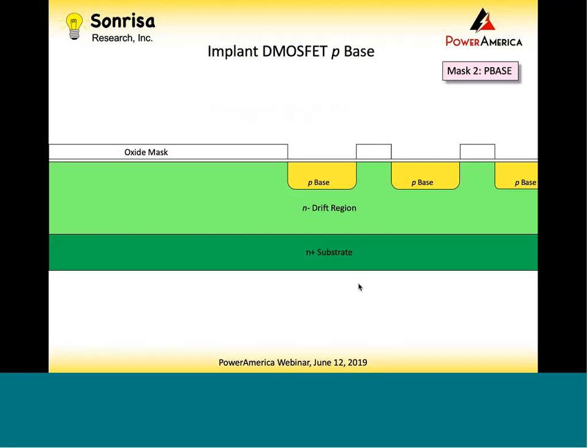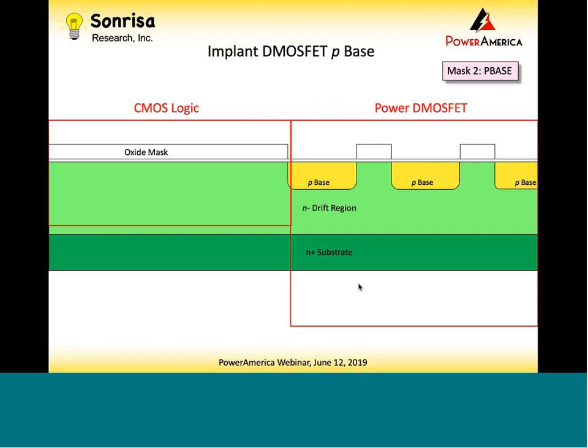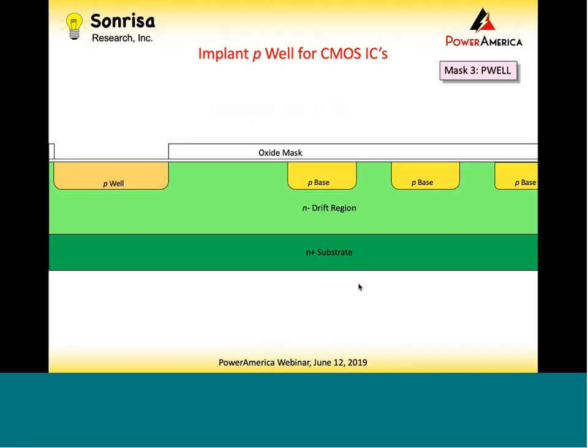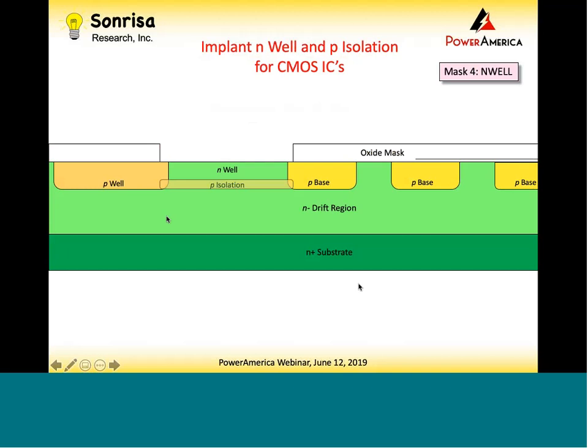So we do a P-base implant, and we're going to put the DMOSFET on the right side of the picture. On the left, we're going to build our CMOS logic, and we're going to isolate it from the high voltage that's on the drain. So the first step of the CMOS is to implant the P-wells. This could be the same implant as the P-base, but initially we're making it a separate implant. We then implant this region here, which is our N-well, and it's isolated by a deep P isolation implant in the same mask, in the same implant step.